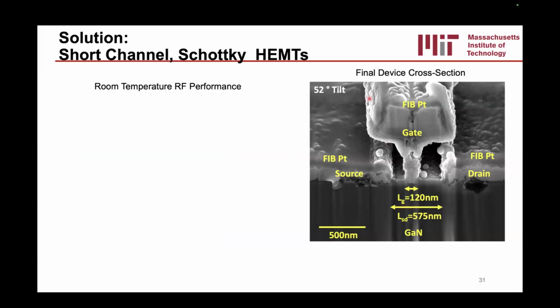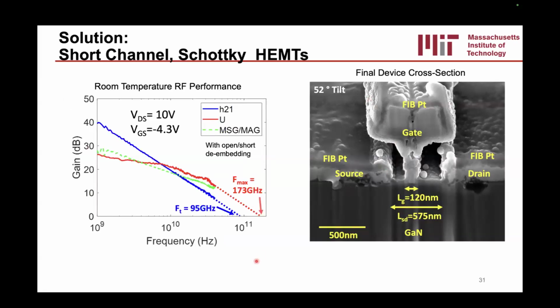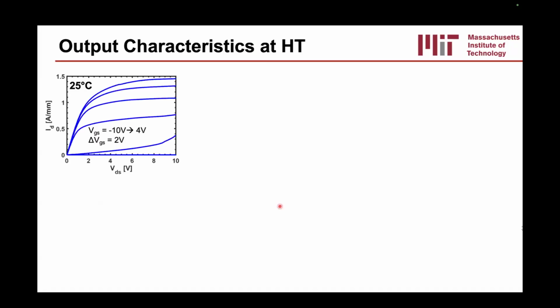And so using this scaled device, we can then see that the RF performance at room temperature is really good. Its fTs are around 95 gigahertz, fmax is around 173 gigahertz. So truly a 100 gigahertz device at room temperature. And we wanted to understand how the DC characteristics of the device are going to change as a function of temperature.